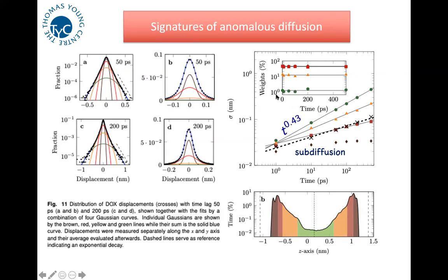So just look at this right-hand panel, and you'll see there's the root mean square displacement of a molecule. There's the time along the bottom, log scale, and the slope would be 0.5 in Brownian diffusion. And in our case, it turned out to be, well, it varied according to what part of the channel the molecule was on. So Amanda was able to sort out the distance covered and the diffusion, which was of the standard Gaussian Brownian type, for certain regions of the channel. Where you were near the walls, it was very anomalous. You got a slope which was much flatter, with a time exponent much flatter. In the middle, it was much closer to Brownian. And when you combine those in the right proportions, you could reproduce the statistics of the diffusion very well. So that was my introduction to anomalous diffusion.